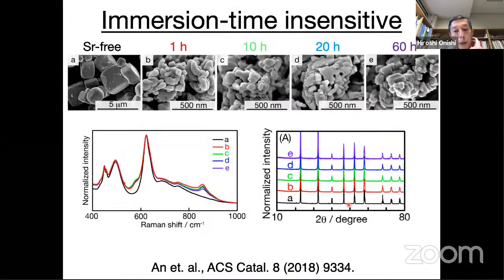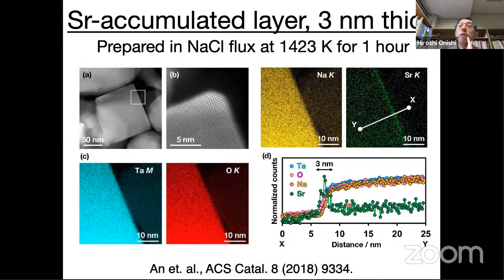So why? We did a transmission electron microscope observation. So these are microscope views. We can see the square particle, and also very good, well-ordered atoms in the crystal. And further, we conducted the elemental mapping. This means the local concentration of tantalum, oxygen, sodium, and strontium in one particle at the same place.